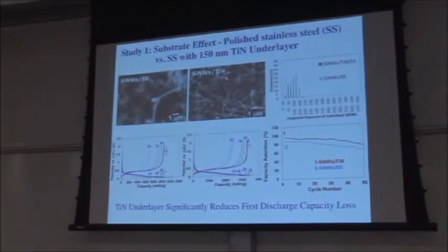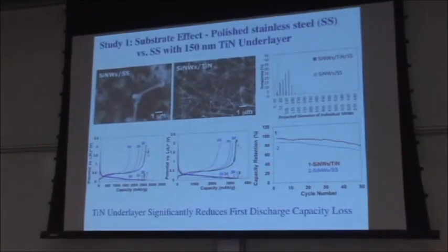So the first thing we did, before we even got into thin films and coatings, is we started playing around with growing silicon nanowires. There are different ways to do it, different methodologies reported in the literature. And typically, you can't grow silicon nanowires on your standard copper anode backing. What you have to do is grow them on stainless steel, because when you grow silicon nanowires, copper would form silicides, and you would not have a real electrode afterwards. So people either grow them on stainless steel backing, or you sputter some kind of a barrier film and then grow the nanowires on the barrier film. So we did it both ways. We grew them on very well-polished stainless steel battery backing, or we grew them on a titanium nitride layer sputtered onto very well-polished stainless steel